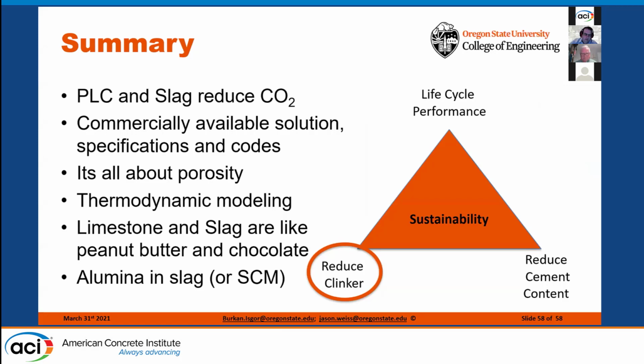So in summary, and we'll then start to go to questions, Portland limestone cement and slag can be really used together in a very, very compelling way to have a substantial improvement on the CO2 footprint. This is something that's immediate. This is something that's now. This is something that we can start using today, which can have a huge impact on the carbon footprint and really be beneficial for the overall industry. There are substantial commercially available solutions. As Doug mentioned, this is really leading into specifications. This is ready to be used in codes. It's an off-the-shelf solution to help the overall process. It's really all about porosity.